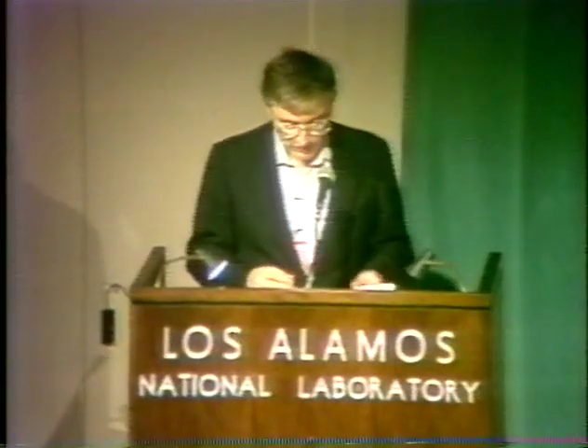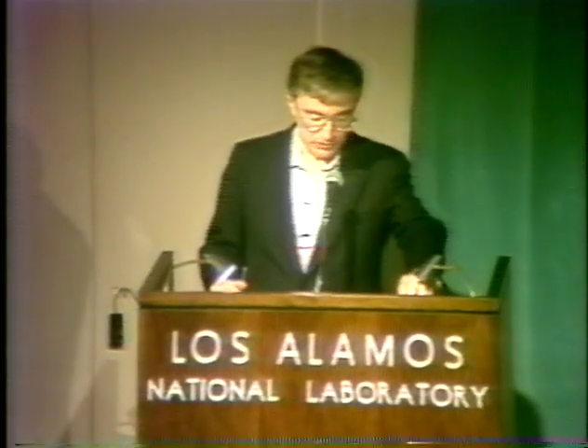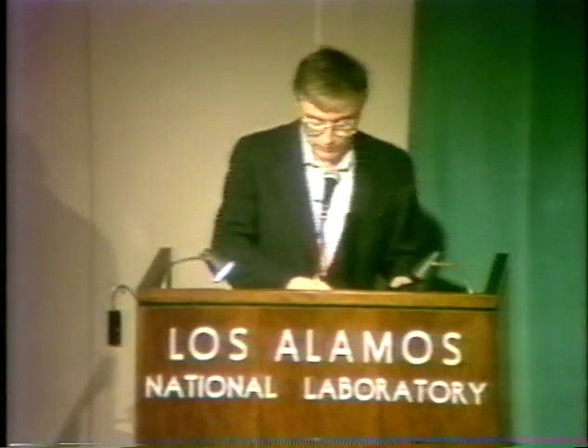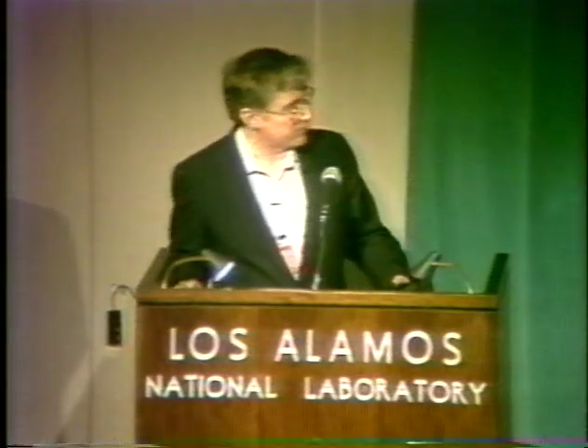So we designed a rather far-fetched experiment, and that was hanging a cube of palladium into a large volume of D2O electrolyte for some months. We got a negative result. We then made some modifications to the electrode. We changed the current density sharply, and a few hours later, we discovered that the cube had vaporized most of the equipment around it. So from then on we decided to change the experiment, which we did. We started over at a very low level, and for the next 5 years tried to be a little bit more careful. And the reaction then which we're considering, if I could have the first slide.